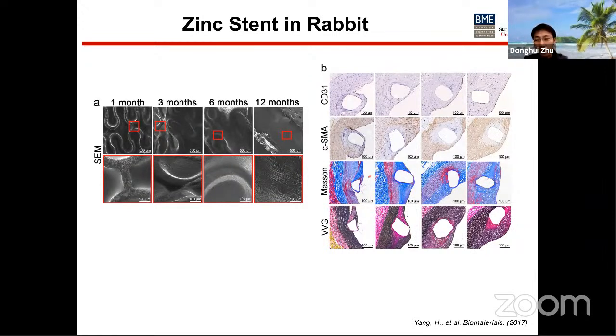The histological staining shows abundant collagen formation and fibrous elastin at 6 and 12 months. The extracellular matrix appeared to be very normal, indicating good biocompatibility of the zinc stent material.